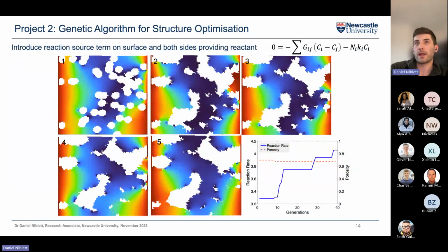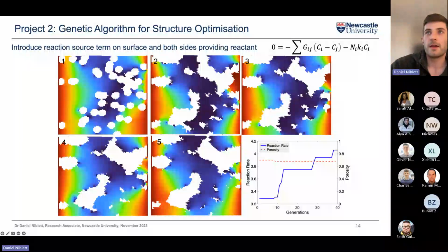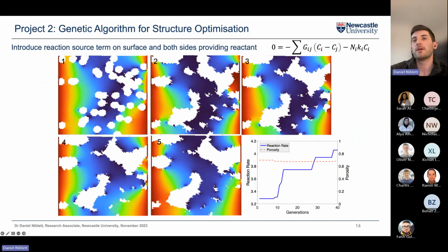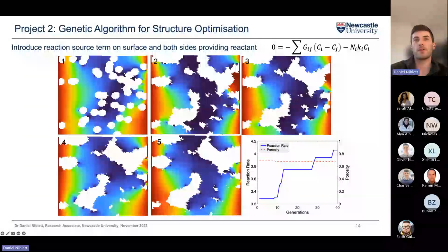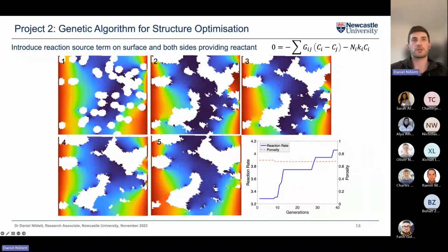So to make it more complex, I then added a reaction source term, just an arbitrary reaction source term on the surfaces of the particles, where I forgot to mention the white parts are the solid particles in this instance, and the color around it is the concentration field. And by implementing a reaction source term, well, it's actually a sink term, then I can tell the algorithm to instead optimize for reaction rate, which is this blue line here. And as you can see, this is what the microstructure evolves to over the generations.